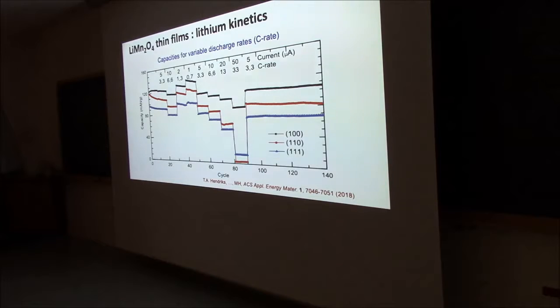Yes, there is. So these are even the discharge rates we would show you, because in this case we did both of them at the same speed, to do both of them fast. So this is something you have to study, what the difference is, but both of them will have an effect on your material. If you try to do it with too large a current, you're not able to get all the lithium in, or later to get all the lithium out.